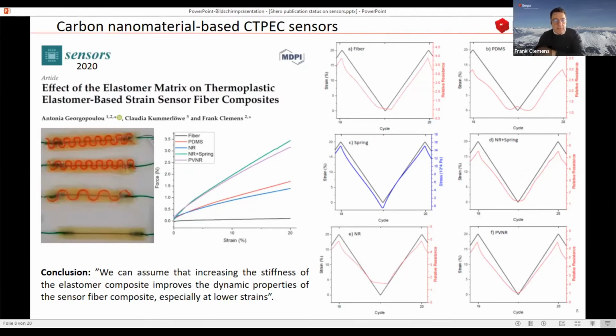And when we looked a little bit closer at these mechanical properties, we saw that we could make two classes. One class was with materials which have a high stiffness, these matrix materials, and the other one, they had a low stiffness. And you can see that for the high stiffness materials, we get good sensing behaviors, and for the low one, we have the secondary peak, or we have here a plateau, which also does not give us the possibility to measure low strain. So according to these results, we thought, okay, the sensor is always the same, but what we see is that the matrix affects the sensor properties quite strongly.